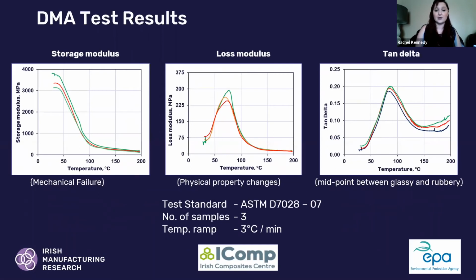These 3 graphs are the results that you get when you do dynamic mechanical analysis, or DMA. This gives you the storage modulus, the loss modulus, and the tan delta. Each of these gives you a Tg, which, as I said earlier, is the softening point of your material. In the storage modulus, it's normally the lowest value of Tg, which is related to the mechanical failure. The loss modulus Tg is related to the physical property changes and its strength. And then your tan delta is a higher Tg value, and it's the midpoint between glassy and rubbery, where it's a bit leather-like. The Tgs that we used, we took from the loss modulus because it was the median value and it was related to the physical property changes, which is what we were focusing on.